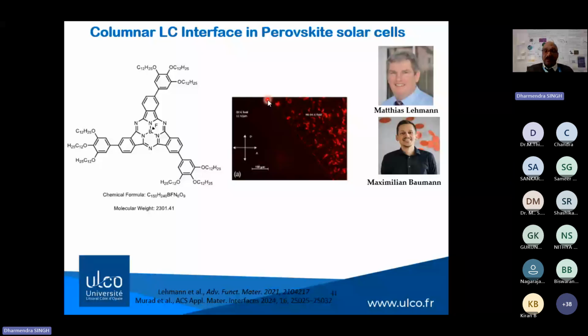One of the problems with these molecules is that they are non-polar, their dipole moment is around 1 to 2 debye, so they do not show any influence with the field. Another system was developed by our collaborator Matthias Lehmann in Germany, and his PhD student got a 1 month fellowship to work in my laboratory to overcome that. They developed a subphthalocyanine based system, and this molecule can be oriented using an externally applied field.